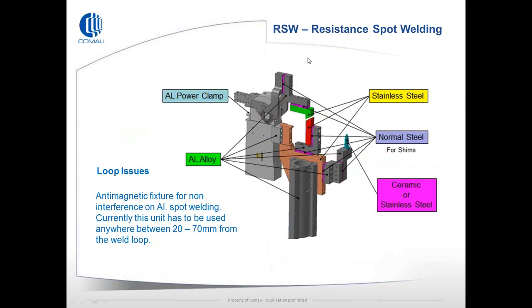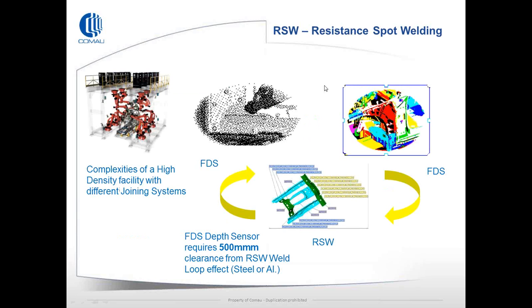Some considerations when using resistance spot welding, in particular with aluminium: because of the high currents required, maybe up to 40 or 50,000, it does have an effect on the tooling and the surrounding areas. So the tooling and the fixturing unit shouldn't be within approximately 20 to 70 mm of the actual resistance spot welding position. Other considerations apply in, for example, a high density facility that's simultaneously joining with different processes.